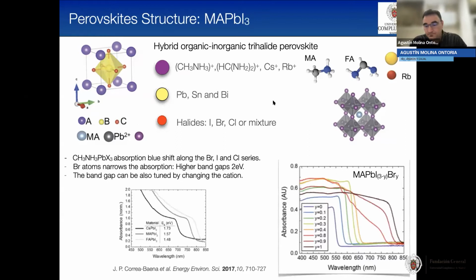So if we modulate, or change the ratio of the composition of the perovskite, we can change its optical properties. For example, going from iodine to bromine to chlorine, we are blue shifting the absorbance. Here, you can see very clearly that if we increase the amount of bromine, we are widening the band gap, and with only 3 bromine here we absorb until 550 nanometers. If this perovskite is all iodine, we can extend the absorbance until 850.